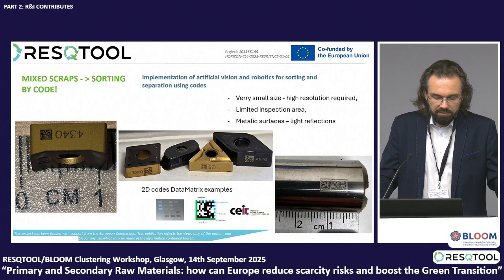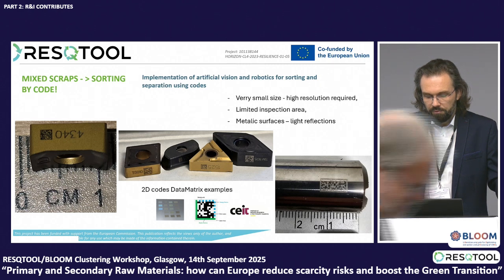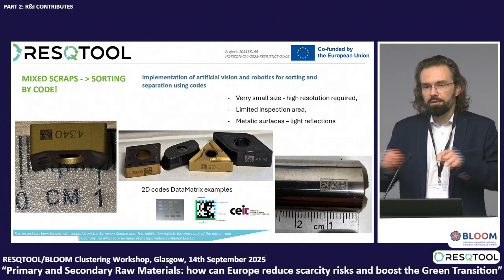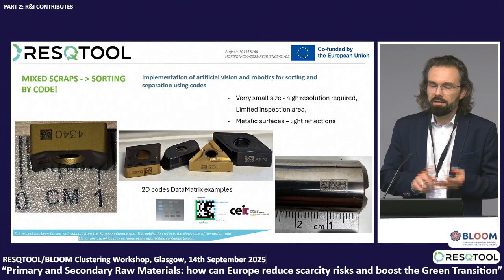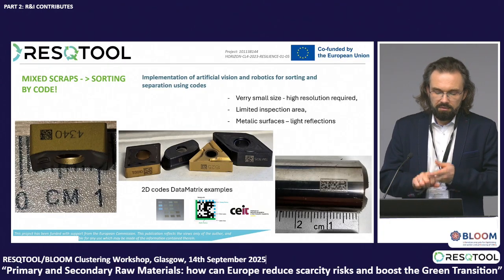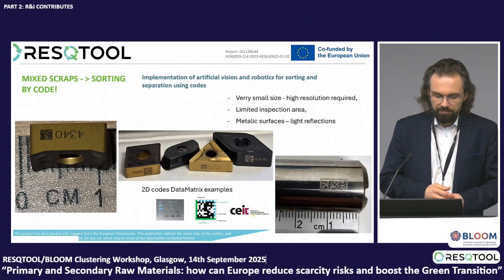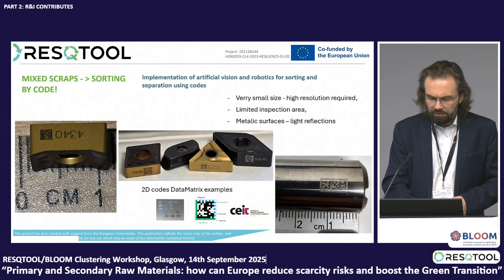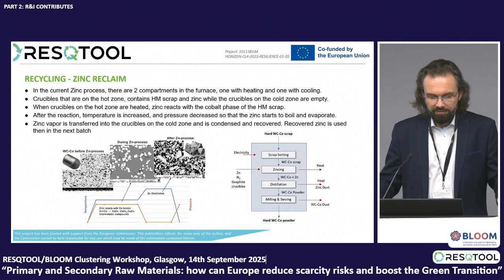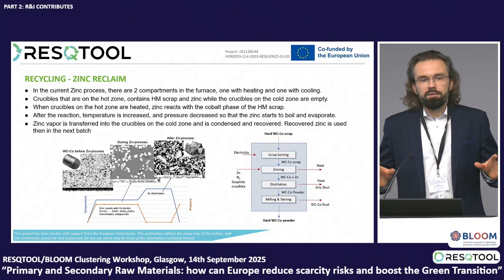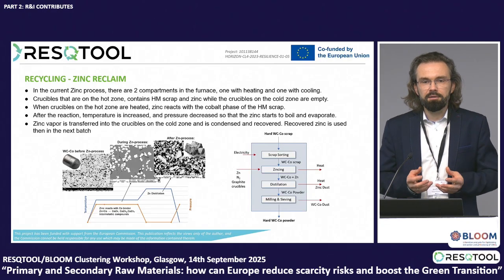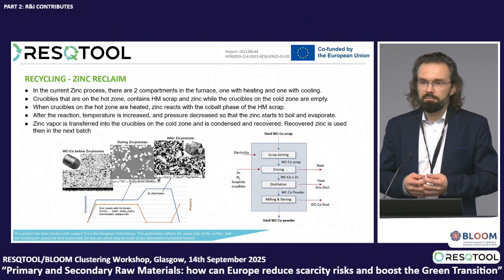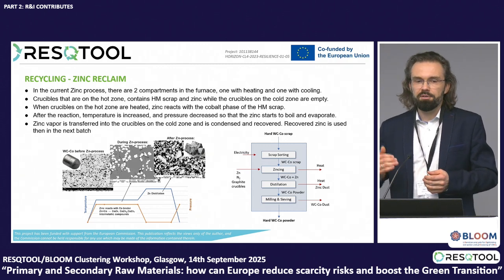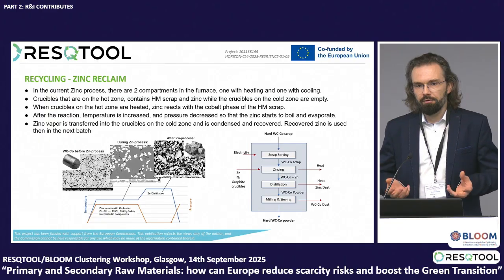So we have some scraps already coded with some 2D codes, and we want to identify them by the code, and then to sort them accordingly with the higher accuracy, with the metal contents, grain size, and the chemical composition of the ingredients. This is very demanding. We are developing the methods for that. But next steps, after proper sorting for given groups, we can then recycle them in the best manner. The best manner means with less energy, with the best result, with recovery of most of the parts.